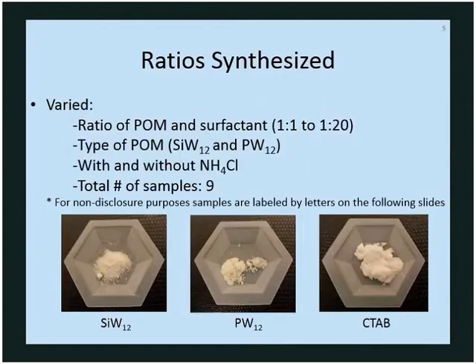So synthesizing ratios vary in percent concentrations of polyoxometalate to surfactant, ranging from 1 to 1 to 1 to 20 ratios. And the type of polyoxometalate used was varied between silicotungstic acid and phosphotungstic acid. And then we also added ammonium chloride salt to convert it from an acid to a base to see if that would have any effects on the anti-wear and friction properties as well. A total of 9 samples were synthesized in oil.